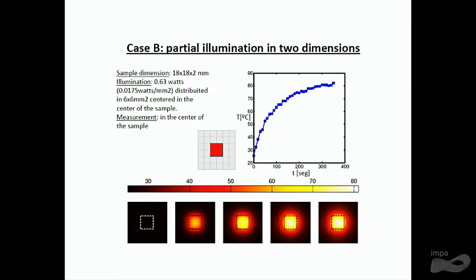We have prepared several examples with different illuminations. Essentially, we changed the size of the illumination. We kept the density, and that made the total power incident onto the sample also change. That gives place to different final temperatures at the end of the experiment. The experiment takes from 0 to 350 seconds. And this is how temperature evolves inside the sample. So remember that our objective was to focus the light into a place and to produce heat in a confined region.